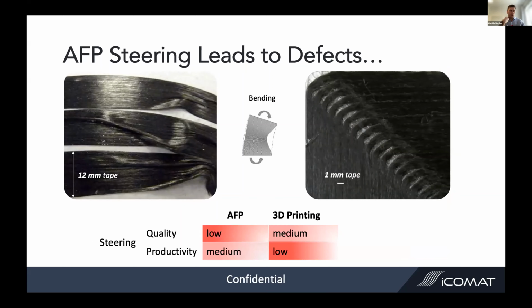Now, one way of doing that would be to bend the tapes or bend the fibers. Unfortunately, the physics of this is not great. As you can see in the images here, automated fiber placement technology is rather limited by just turning the head and bending the tapes. You have a differential of the inner and the outer radius of that tape, which means you get buckling and folding of the tapes, and it basically looks like a bit of a mess. Even with very narrow tapes like 12mm wide, you get a bit of a problem.